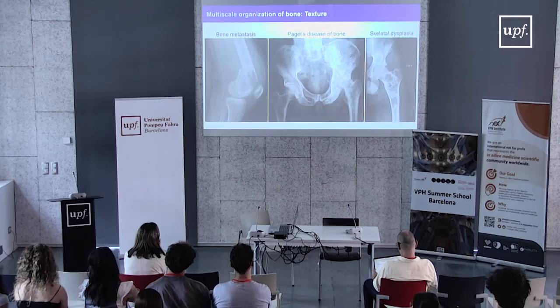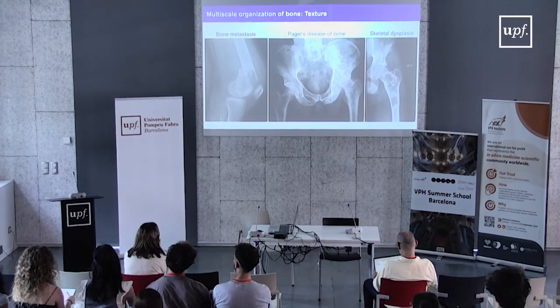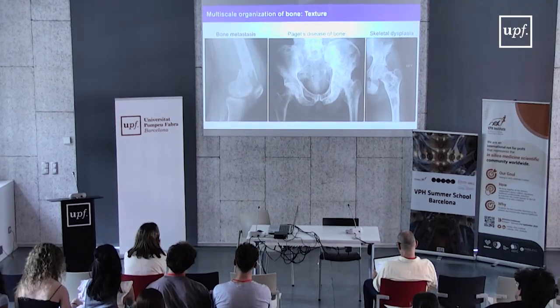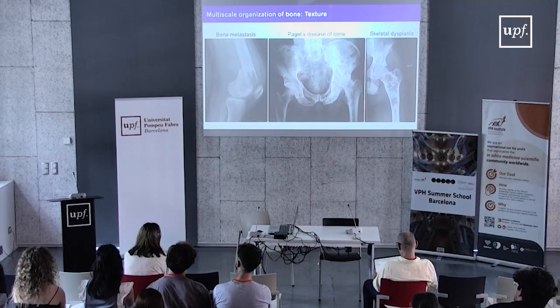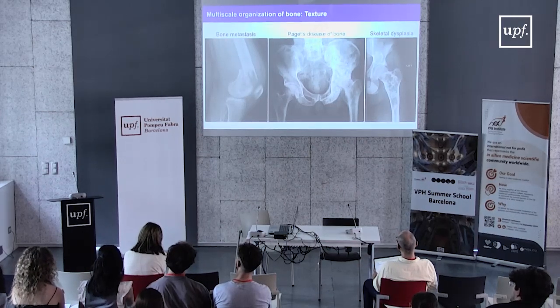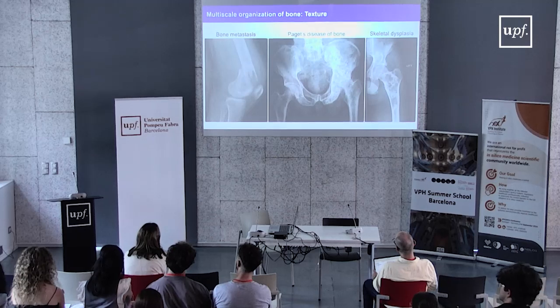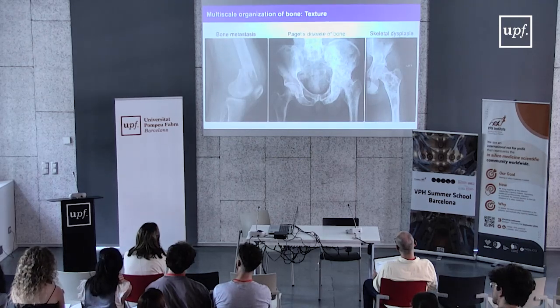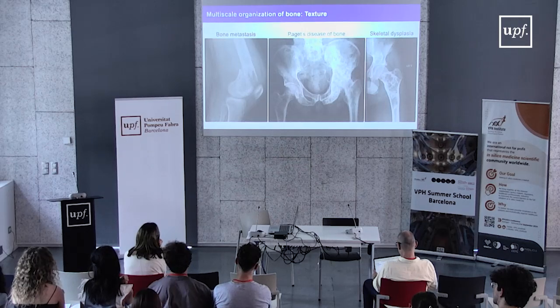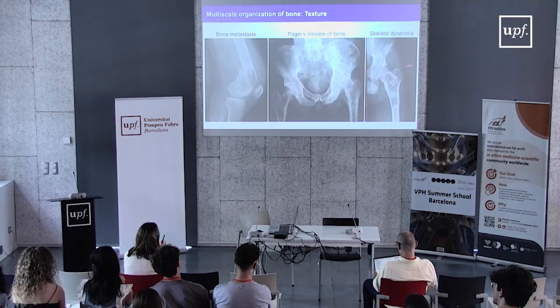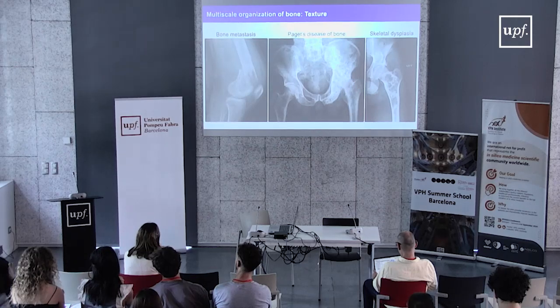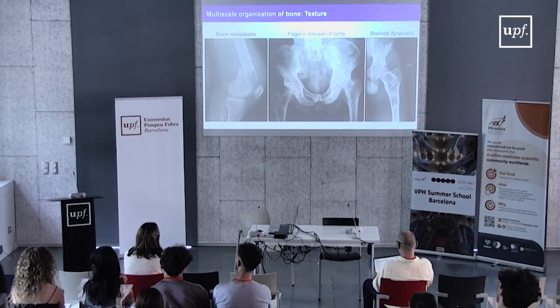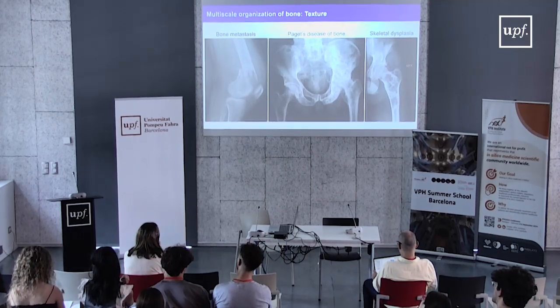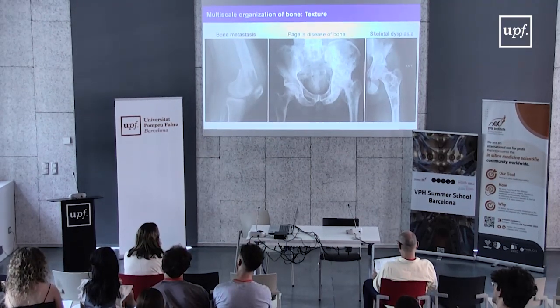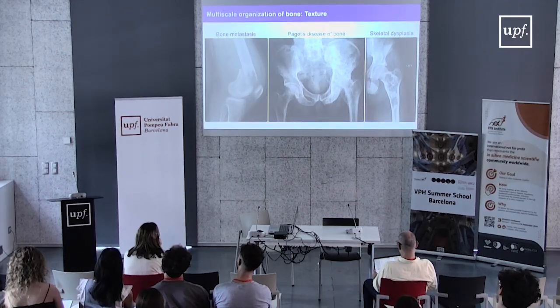When you don't have this organization into lamellar bone, you are prone to develop bone fragility, and it's exactly what is seen in bone metastasis, where you can even have more bone material, but a material that is not organized with the texture that it should have and doesn't resist to the different stress, and you get fracture. It's exactly also what you can see in skeletal dysplasia, where you have an abnormal deposition of the bone. So here again, it's not a problem of low bone density, but really a problem of poor quality of the bone, and you get fracture. And it's also what you get in Paget's disease of the bone. So the texture is really important to have the maximum resistance to fracture.